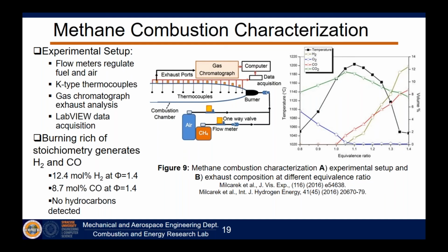But as we increase the equivalence ratio, meaning we now have extra fuel and not enough oxygen available to completely oxidize it, now we start to see significant carbon monoxide and hydrogen being generated at higher equivalence ratios. So even at an equivalence ratio of 1.4, we saw about 12% of the exhaust was hydrogen and about 8% was carbon monoxide. Now you might ask yourself, why did you stop at 1.4, right? Just keep going. Well, the challenge with combustion is typically we want to operate near stoichiometry because that's where the reactions can happen very readily. But if you become very fuel rich, the reactions can't actually sustain themselves. There's not enough heat release from the flame to keep the reactions going, and so the flame ultimately will extinguish as you get extremely rich. And so in our case, at an equivalence ratio of about 1.4, just beyond that, the flame extinguishes. That's kind of the end of the story for this kind of technology at this point.